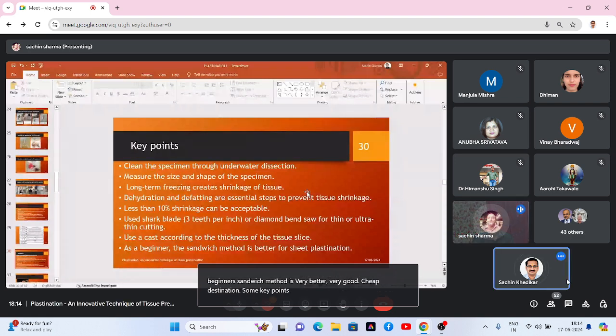Some key points to be noted here: clean the specimen through underwater dissection properly, measure the size and shape of specimen during sheet plastination, measure the weight of this specimen so that we can assure the shrinkage. Long-term freezing of tissue creates more shrinkage, so be careful about that. Dehydration and defatting, or we can say acetone bath, are essential steps for preventing tissue shrinkage. Without these procedures, we cannot get the exact structure we want. Now, less than 10% shrinkage can be acceptable, but more than 10% is not acceptable.